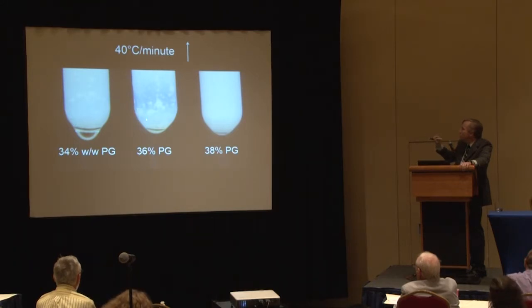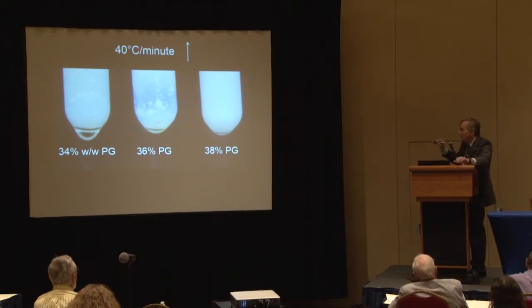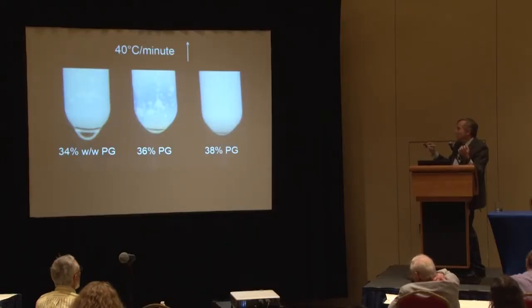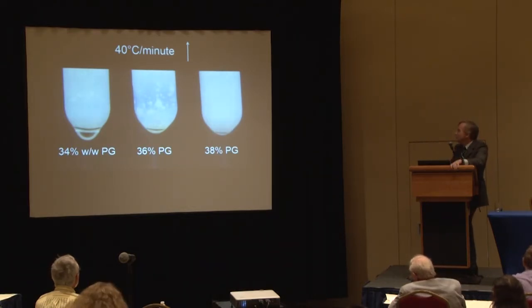But this solution is completely devitrified, but it's semi-transparent. All you see is a sort of bluish opalescence here. And I learned from Austin last night that this is actually a dangerous experiment to do because when transparent devitrification occurs, it happens at such a low temperature, so close to the glass transition temperature, that the solution is still extremely rigid, and the sudden formation of this amount of ice can actually explode the test tube and send glass flying everywhere. So next time I'll be sure I wear goggles when I do this, or a face mask or something.